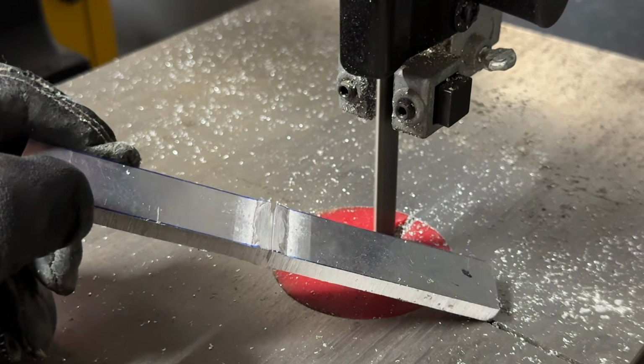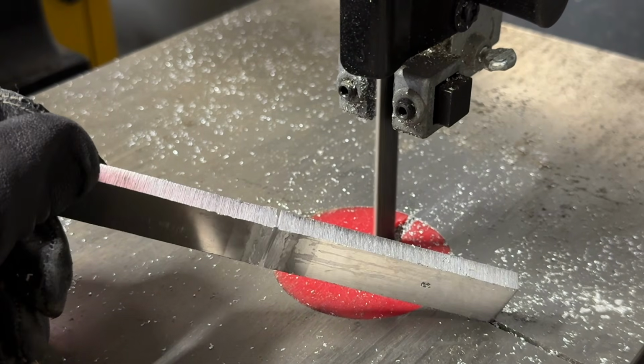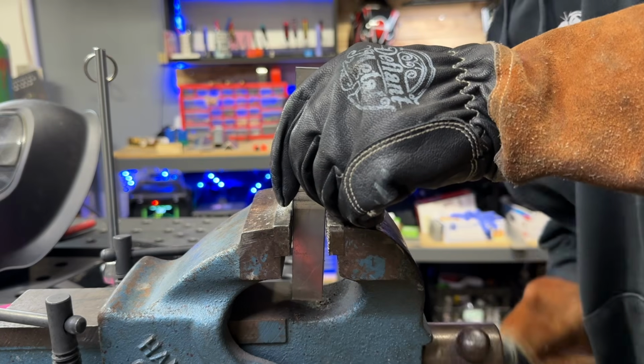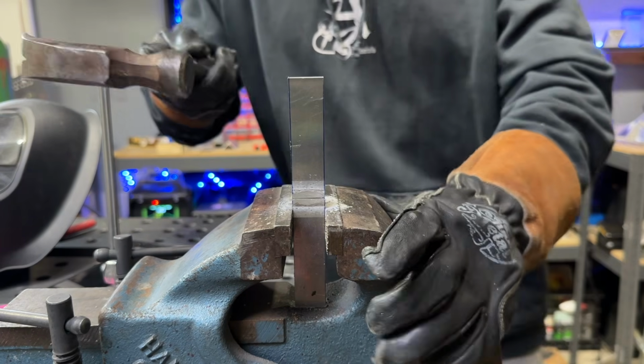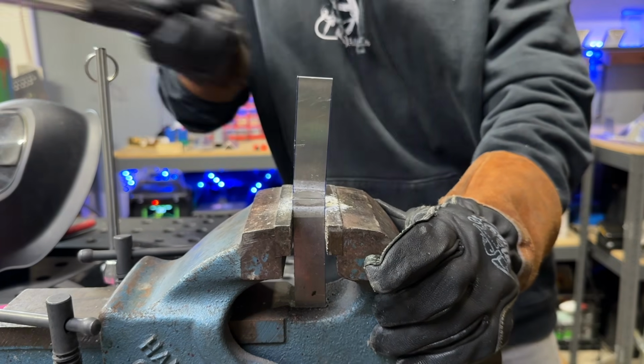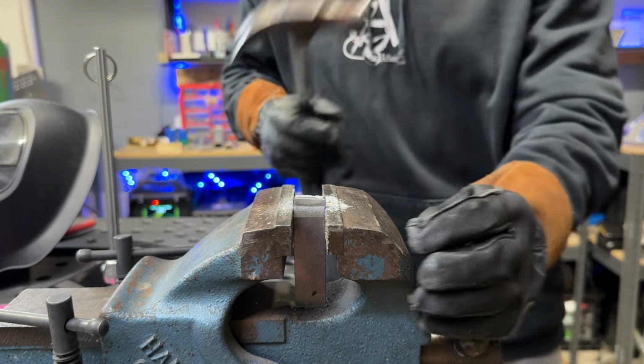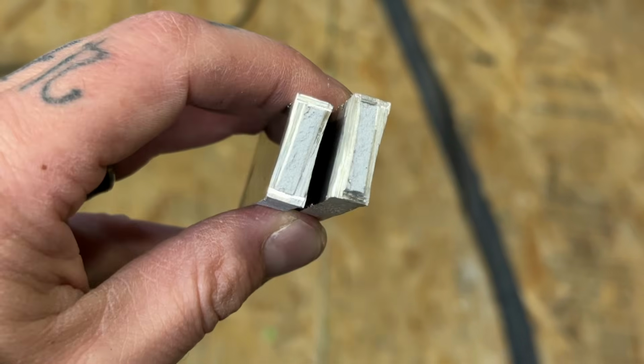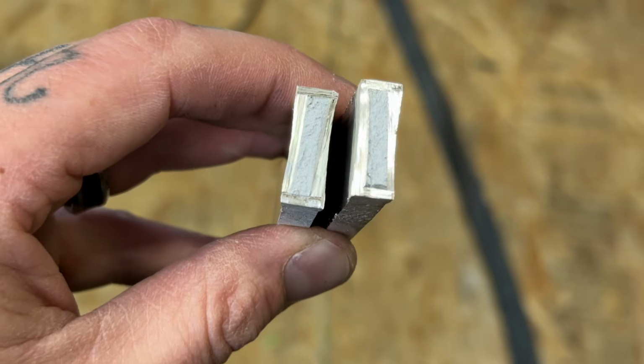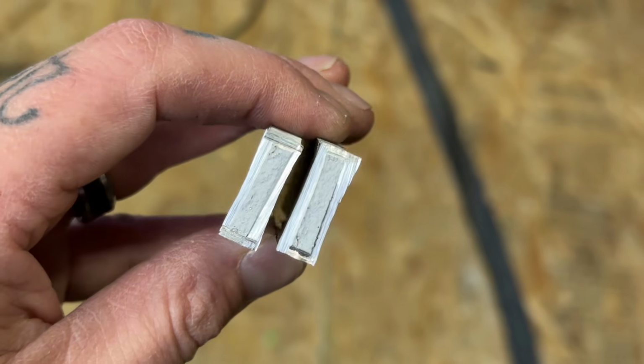It's only about 1/16 of an inch deep, but what's going to happen is you're then going to fix it in a vise or something stable to hold it still. And using a hammer, you're going to hit it and try and break it. In this circumstance here, you can take a look at the inside. We don't see any problems here for the most part. We can see that the penetration has gotten through the complete welding coupon.